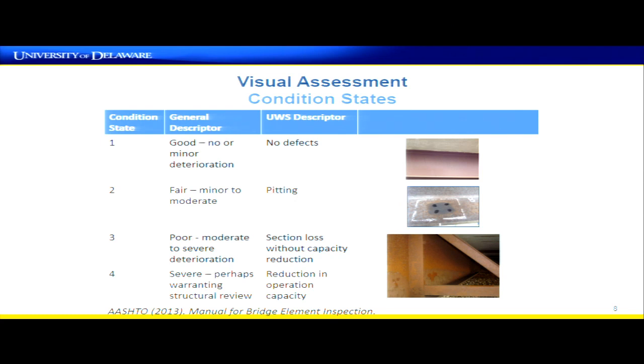So visual assessment of weathering steel. At the time we did this research, most of the owners had already adopted the guidelines in the AASHTO 2013 Manual for Bridge Element Inspection, which has a condition state rating scale of 1 to 4, 1 being the best, 4 being the worst, which is then applied to every element in the bridge, and then not only that, but also the amount of that material in each condition state.